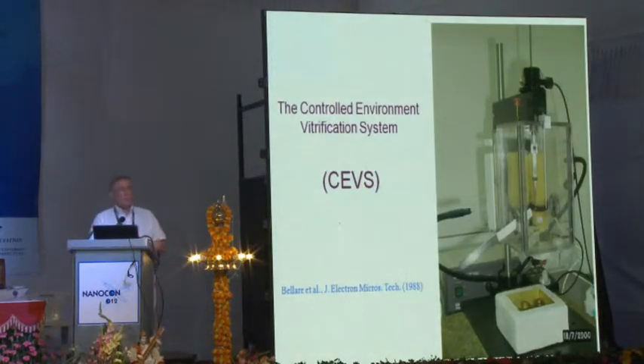Another challenge of these systems is that they are very sensitive to temperature and concentration changes. So you have to make sure that during specimen preparation, you make them in a box like this one here, which we could call the controlled environment vitrification system, in which you control both the temperature and the saturation of the gas phase. If you do that, you ensure that the structure that you capture is the one you have in the vial, the one of interest. And I will show you later on towards the end how important that is.